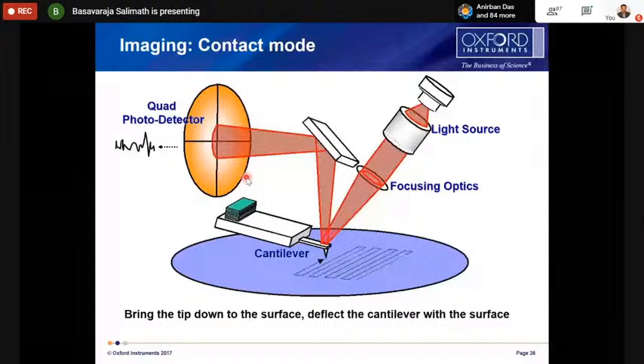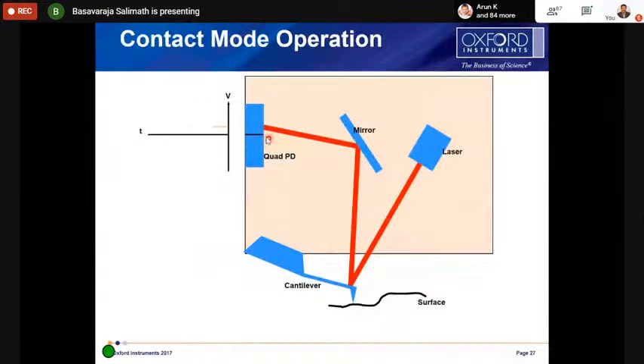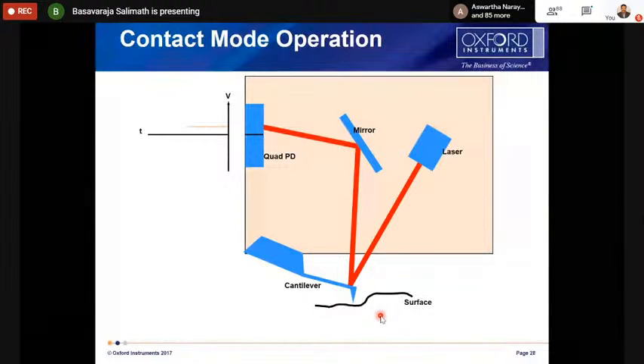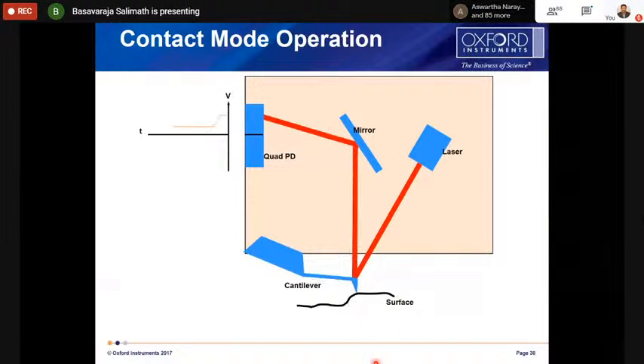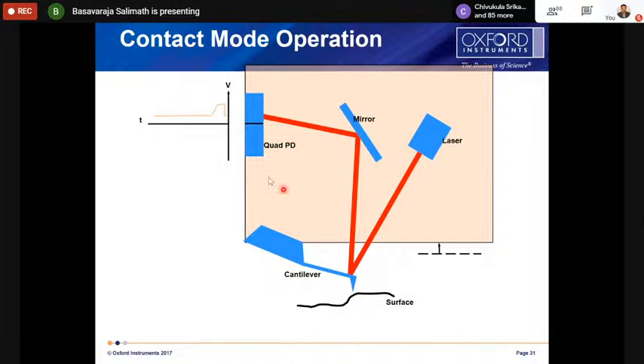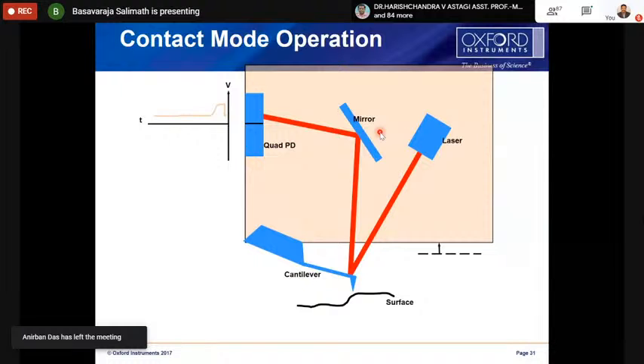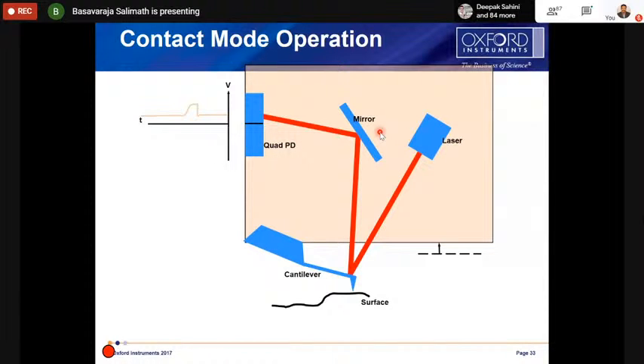You can see this is your surface, and initially the reflected laser in the photodetector is at this place. When the tip goes up, the reflected laser also goes up, but it has to stay constant at the original position. So the feedback will adjust the cantilever Z height, and then it will come back to this position. You can see this height is adjusted, and now it came back to the original position. Like this, it is scanning the surface in the case of contact mode.